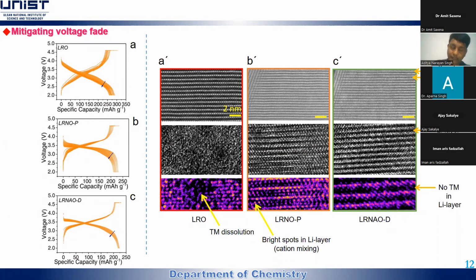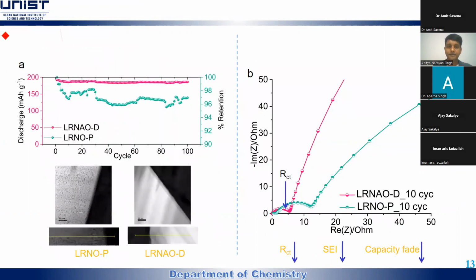And because of nickel doping, the anti-site defects increase. That's the reason people are also aware that they should lessen the nickel content in commercial batteries. But nickel helps in stabilizing the crystal structure. So again, here comes a trade-off. Nickel is a must, but nickel has to be optimized. This is where the research should go on.